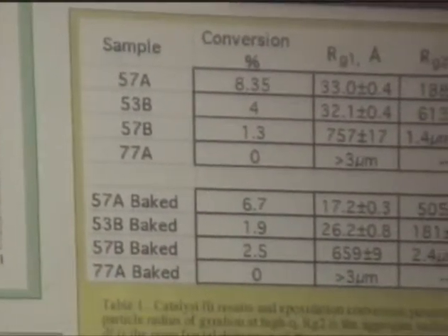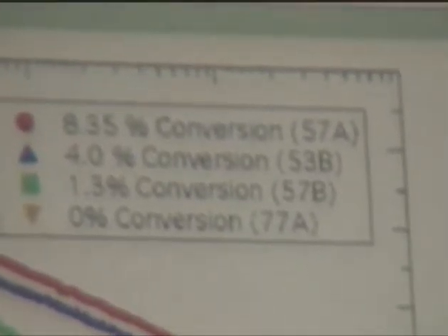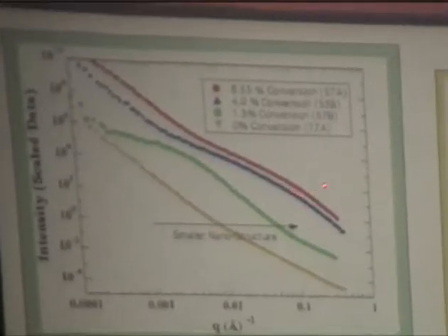Okay, so this is an X-ray scattering curve. This data was taken at the APS in Chicago, the Advanced Photon Source at Argonne National Lab. The reason to go there is that this size, a micron, this 0.0001, you can't access in a lab instrument. The range of a lab instrument is kind of right here, basically to the same endpoint. The advantage is that these are decades in size, so there's 4 decades in size, going from an angstrom to a micron. Okay, 10,000 angstroms is a micron. And you can march across that size scale and look at the reactivity of the catalyst.